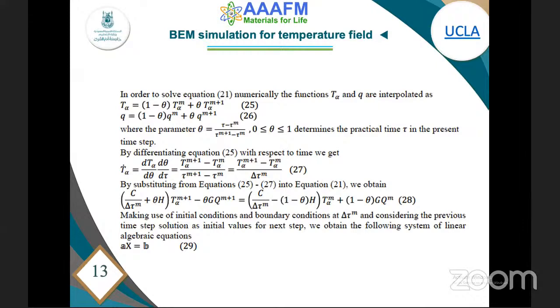In order to solve equation 21 numerically, the functions T, alpha, and q are interpolated as equations 25 and 26, where the parameter theta determines the practical time in the present time step. By differentiating equation 25 with respect to time, we get equation 27. By substituting from equations 25, 26, and 27 into equation 21, we obtain 28.